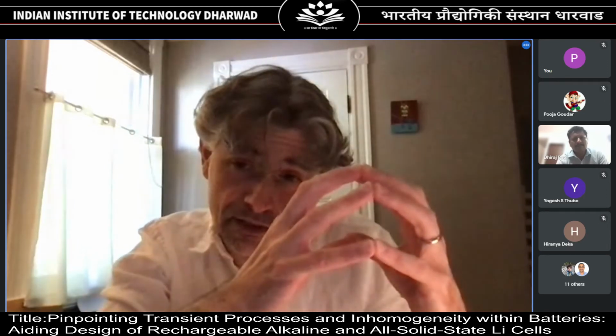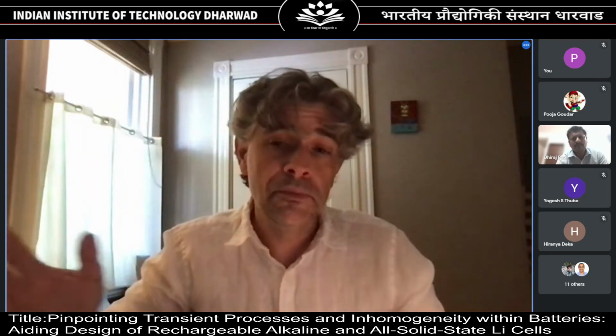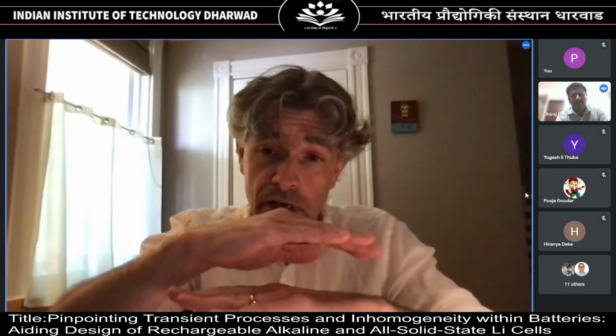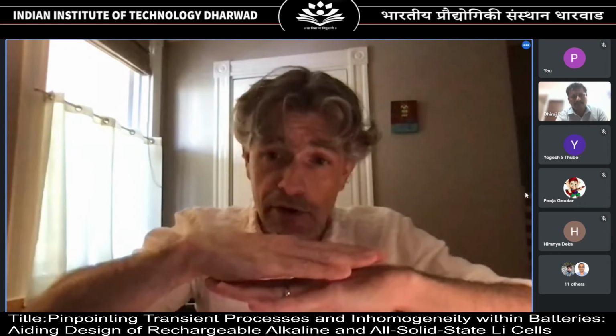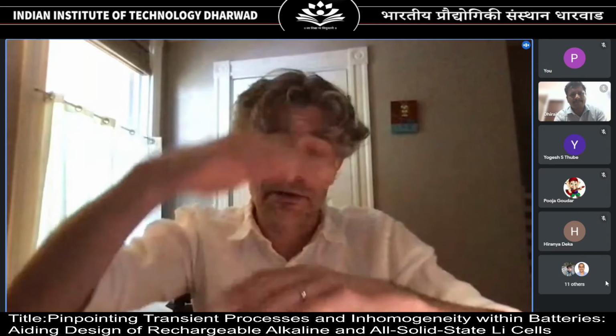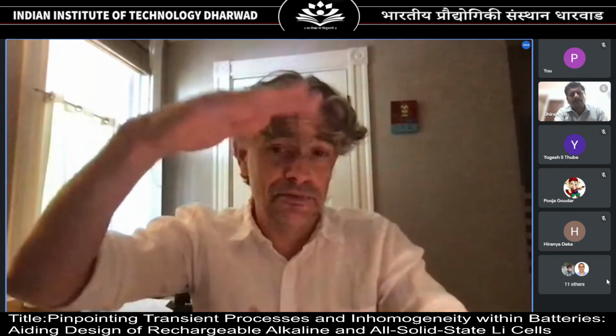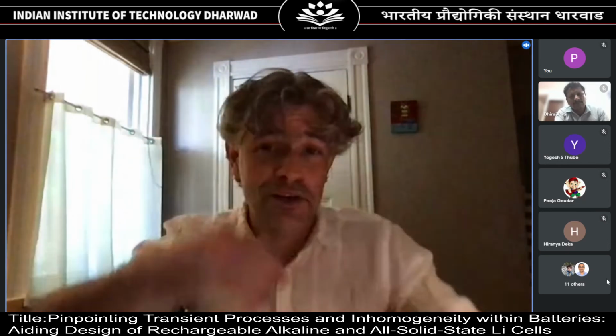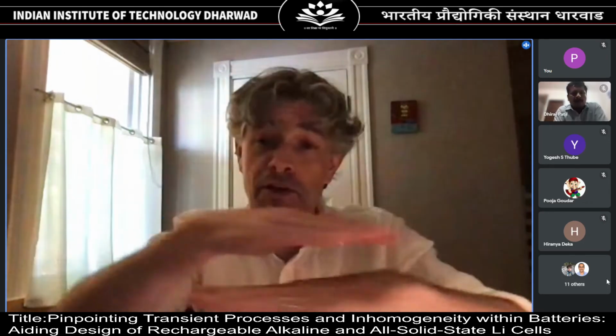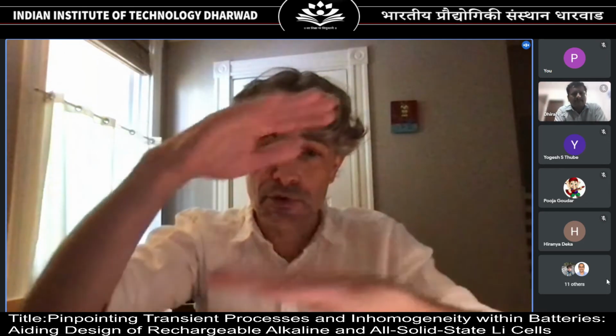Now that undergoes the battery reaction, and the battery reaction is intercalation of lithium ions. So Li+ goes into this material, and then Li+ comes out of the material. Li+, when it sits in the layers, causes the layers to come together. Protons, in the MnO2 battery, cause the layers to come apart. Li+ goes in and makes the layers come together. There are different reasons why, but the layers are negative, and when the lithium goes in, it screens the negative charges and causes them to come together.